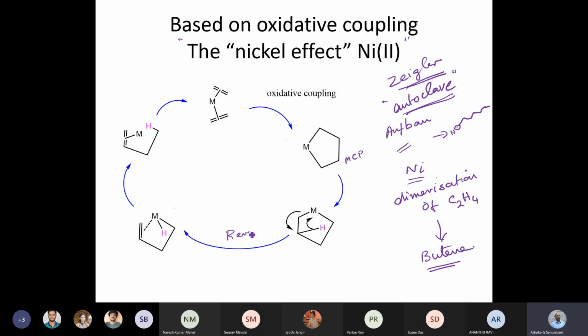Reverse of migratory insertion reaction, right? So if you did a migratory insertion reaction here, you would end up with this. In fact, all these reactions are reversible, and there is no reason why the reaction should stop here, but it does. Nickel has a propensity to do this beta hydride elimination when you have two alkenes coordinated or two alkenes oxidatively coupled. So it invariably leads to dimerization of ethylene to give you butene. So that was a single product obtained as opposed to the long chain system that they were expecting, and so it was dubbed the nickel effect. So anytime you have a surprising result, you better go and examine exactly what caused it. Sometimes it could be a simple impurity.